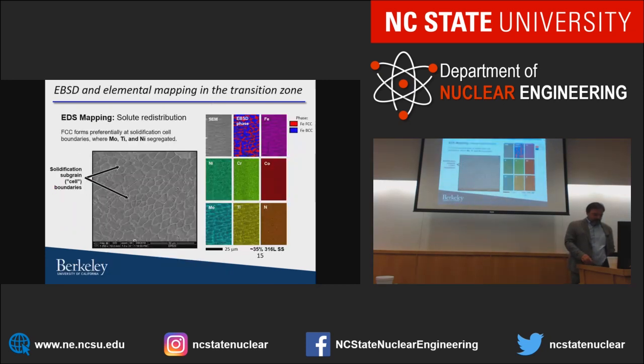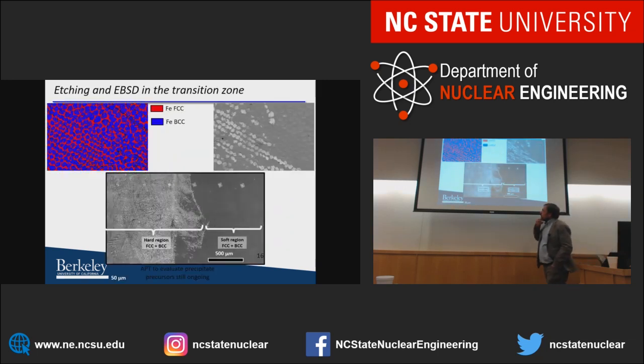So we look a little bit deeper in the microstructure and we find these solidification cells, a little bit of porosity in there. Elements segregate to these boundaries and what have you. But nothing too interesting or exciting so far that would point to this. Then we etch it chemically, and we see that one side, the hard region, which is the mostly maraging side, with the smaller indents, etches significantly, and the 316 side, with the softer, larger indents, does not etch. It goes so far that with individual solidification cells, this one etches and the next one doesn't. So what is it that makes exactly one composition, one layer, etch and the other one not? What makes one 4 times as hard as the one next to it?